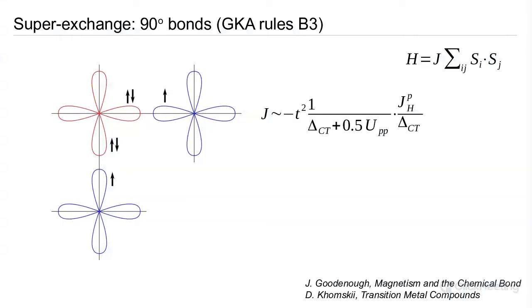Okay, we can just go one step further now with Hund's rules, the GKA rules, and we can think about the interaction on a 90-degree bond. And what we have here is very similar logic applies, but now the interaction occurs via 2 oxygen p orbitals. So we end up with what is effectively a ferromagnetic exchange interaction, where we rely on a Hund's coupling between the electrons on the p orbitals. Like I say, that's a summary of the GKA rules, and these 2 textbooks really give a detailed description.